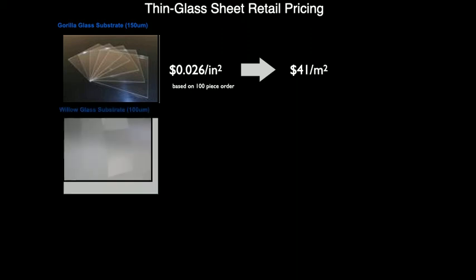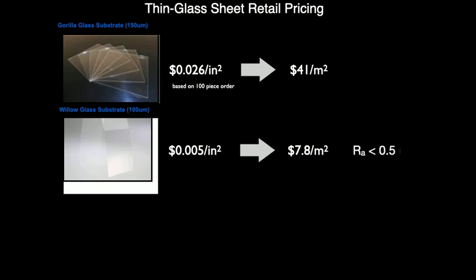If you look at pricing on glass, it's a very different situation. Here's Gorilla Glass, $40 a square meter for a 100-piece order. Willow Glass, also inexpensive, $8 a square meter. And look at the smoothness, or the roughness, should I say, which is less than 0.5 nanometers. So you can get to this kind of fidelity at low cost.